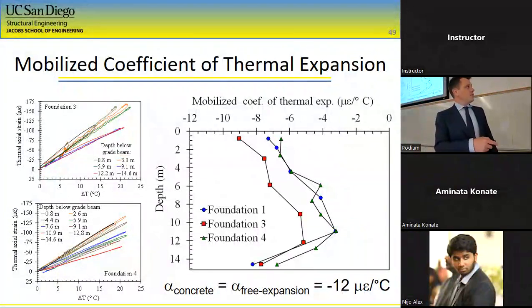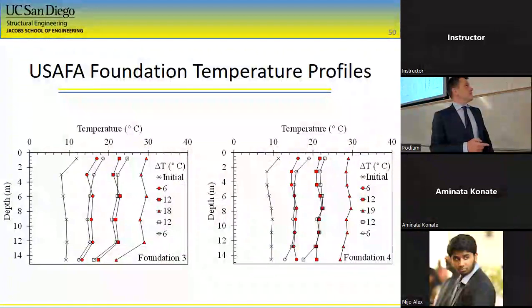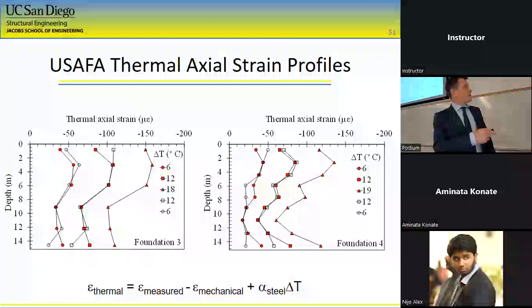If our concrete was reaching the free expansion, which is 12 microstrain per C, then there would be no thermal stress. Here's our temperature profiles, relatively uniform with depth. Thermal axial strain, a little bit higher strains at the top than at the bottom. But because of that pore clean out at the toe, you ended up having the higher strains at the toe.